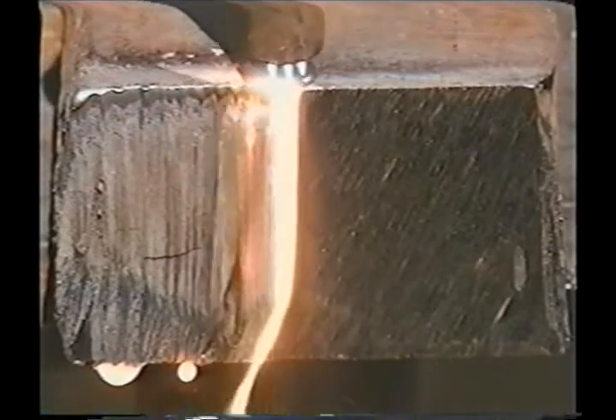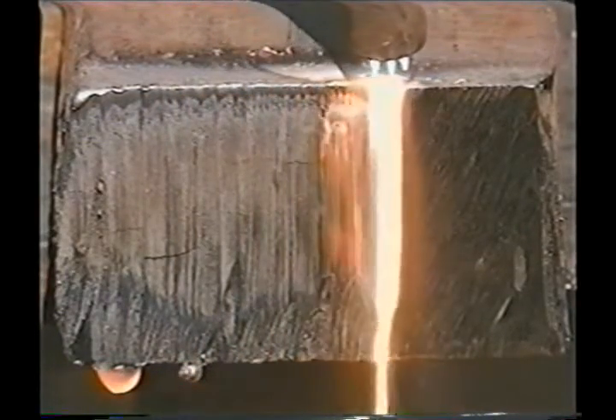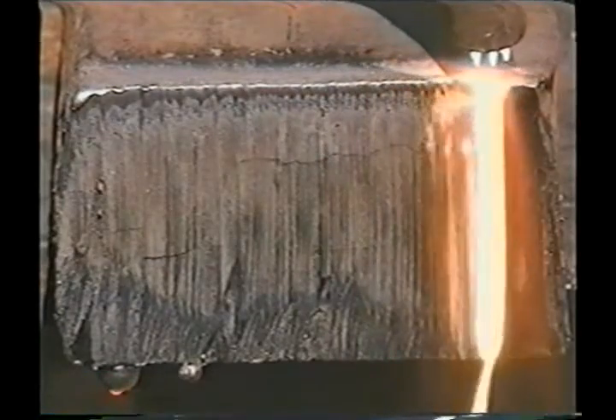Now, the reason you can make a clean, controlled cut on carbon steel is that the oxides produced from this burning process have a lower melting temperature than the metal itself, and the force of the cutting jet blows the molten oxides through the cut before the metal can melt. On some metals like cast iron, stainless steel, and aluminum, the oxides that are created from burning have a higher melting temperature than the metal. So the metal itself is melting before the oxides can be blown away. You can get these metals hot enough just to melt all the way through, but it's difficult to make a clean cut.